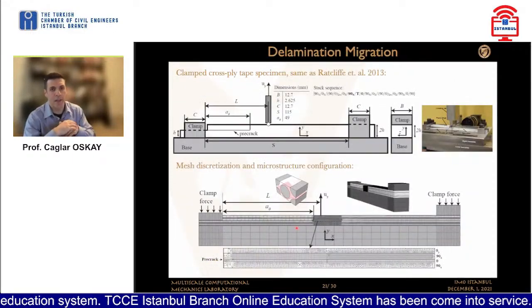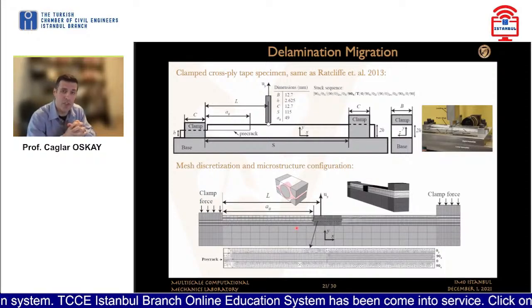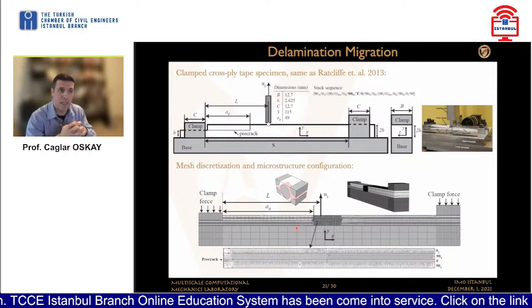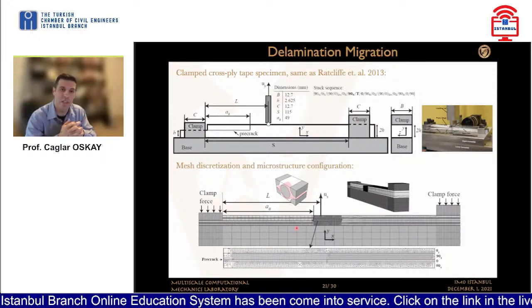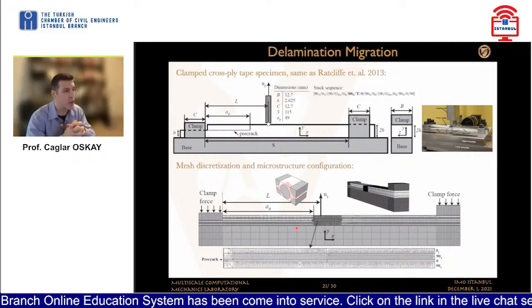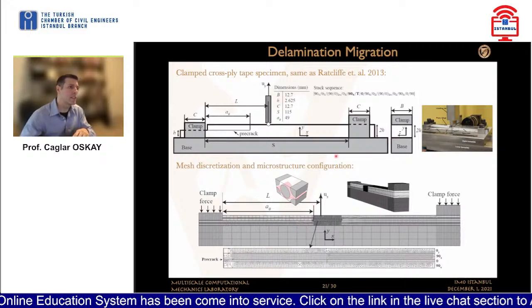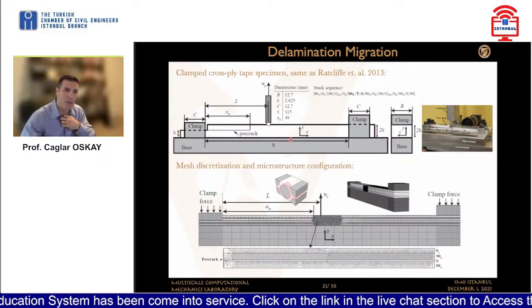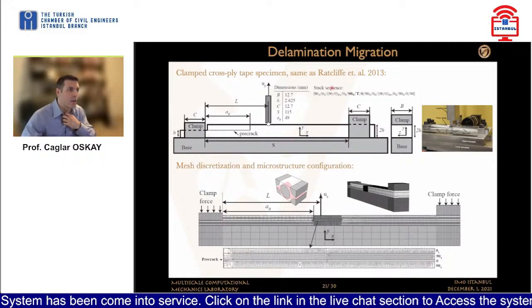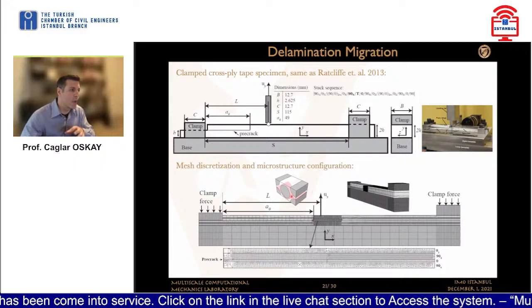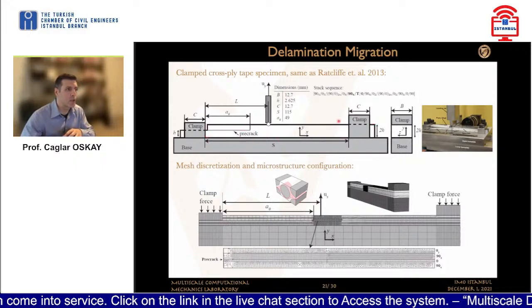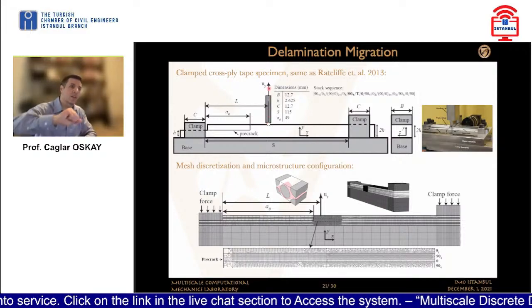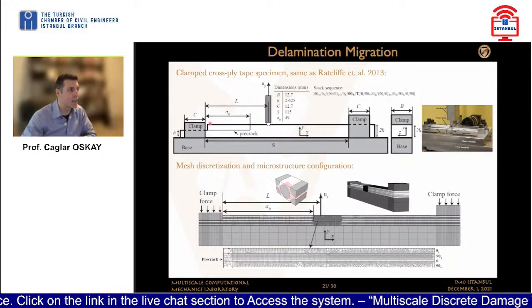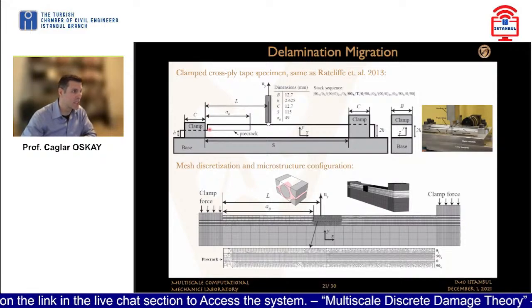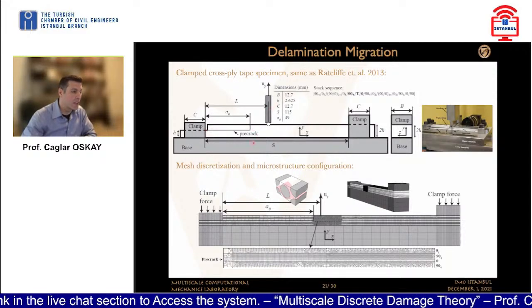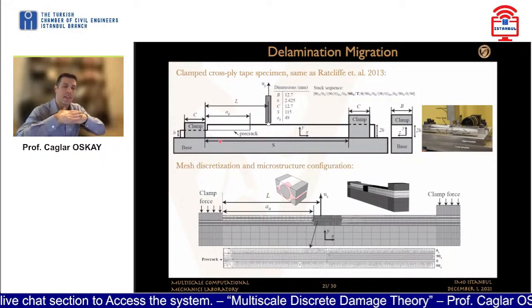Now let's go to the modeling of delamination migration. This is a good validation study for us because, even though it looks fairly straightforward, because of the instability of fracture, it's a fairly complicated phenomenon. And this delamination migration setup, I believe, was invented at NASA Langley by James Reeder and co-workers. The way it is done is that you have a specimen that is put on here. You apply a tension load from the top at a distance L from the left end of the specimen, and you insert a pre-crack at a 0-90 interface.